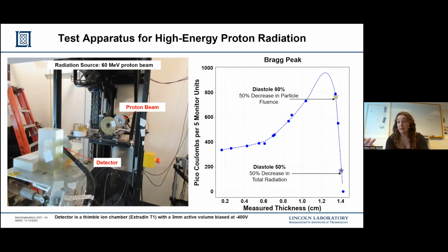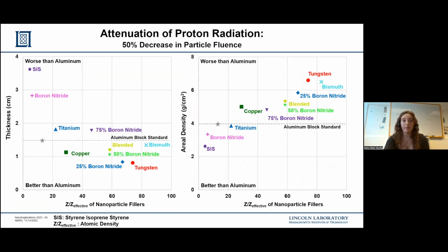At the distal 80%, you have a 50% decrease in particle fluence. This is a 50% decrease in the total number of particles physically hitting your detector. At the distal 50%, you have a 50% decrease in the total amount of radiation hitting your detector. So these are two very important parameters to consider depending on what mission you're doing. We tested both and then recorded both.